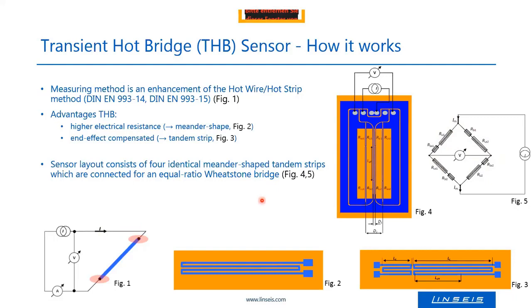Some instrument manufacturers also use hot wire techniques, and they integrate the Wheatstone bridge in the electronics. And before the measurement, it needs to be equilibrated so that this diagonal voltage is zero. In our setup, it is self-equilibrating because the bridge is not in the electronics, it's in the sensor. Before the measurement, every wire is at the same temperature. These resistances depend on temperature, and if all four wires are at the same temperature, then our bridge is equilibrated and we can start.